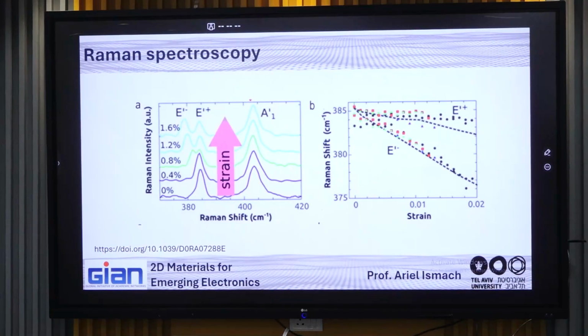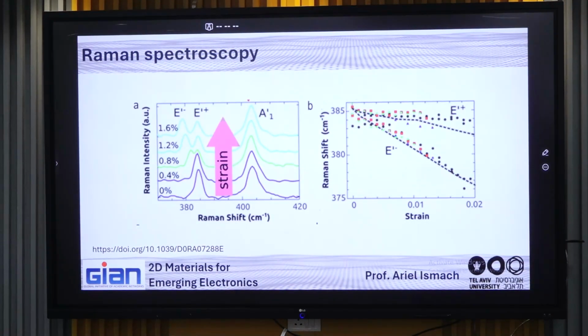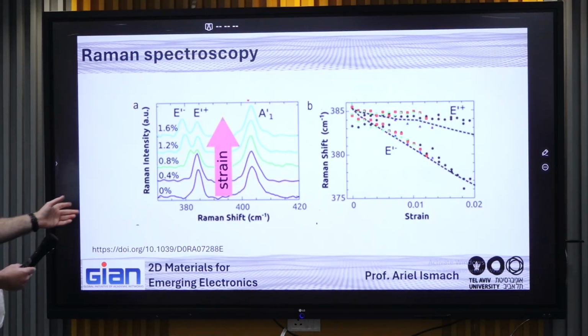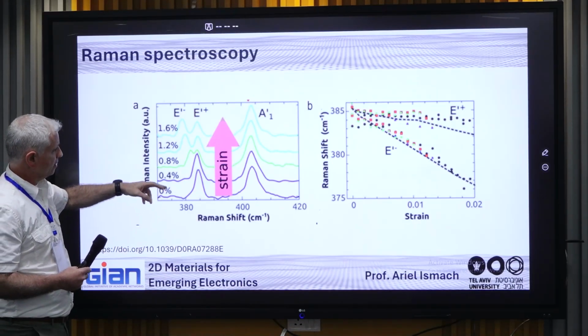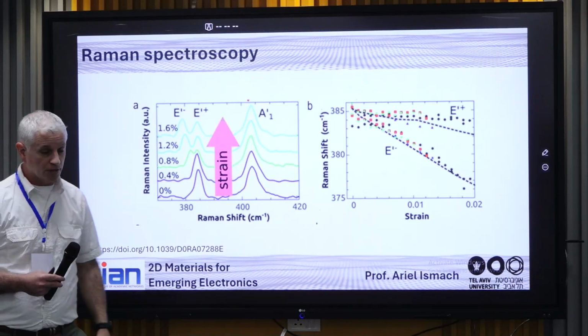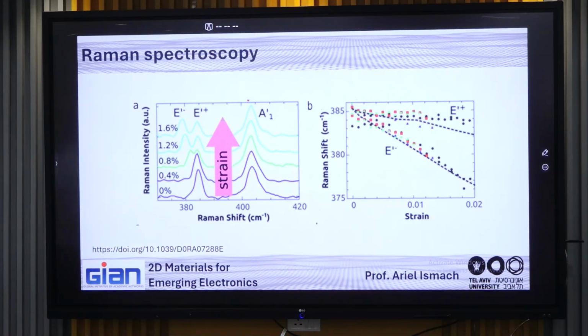Another thing that you can do with Raman is to monitor strain. Not only for TMDs, but you can do that also in graphene. Basically, what you do is transfer your single layer to a flexible substrate, and then you can stretch it, for example, and measure the strain, or you can bend it and also measure the Raman in situ. And by that, you can know the percentage of the strain and check the Raman, and you see that the Raman changes dramatically. It's expected that the vibrations of the lattice will change when you have strain.